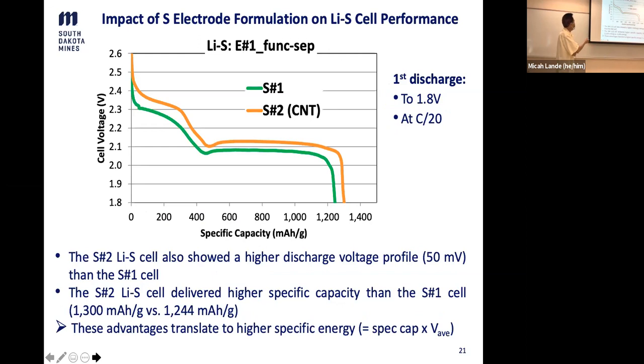Another example I like to show is the impact of the sulfur electrode formulation on the performance. Remember we have S1 and S2, where S2 has CNT in it, and you notice that the discharge curve has a little bit higher profile than S1, and also a little bit more capacity. Although this is not much, by 50 millivolts, if you combine these two together, it leads to higher specific energy. The specific energy equals specific capacity times voltage. So when this all adds up, it has an advantage in terms of performance.